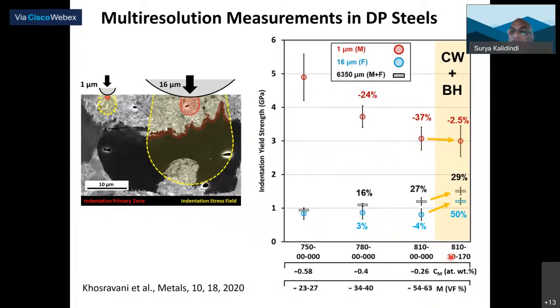But in this deformation and bake hardening process, the martensite remains more or less the same. There's no change in the martensite. But the ferrite now has gotten much stronger because of solute pinning of dislocations. And the effective value also goes up. So by being able to get this kind of information fast on complex materials, we are getting a lot of very useful data that can then be fed into the physics-based models. That's the feedback into the physics-based models.